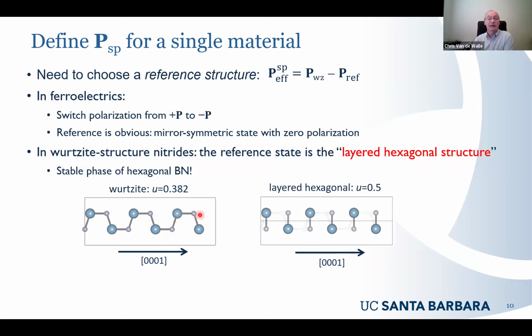But of course, there is flexibility for the atoms to move along the C direction. And they actually, this is the value for aluminum nitride, they settle in a position where U is equal to 0.382. Well characterized experimentally, and this also comes out of calculations. So what do we want to do when we switch the polarization?